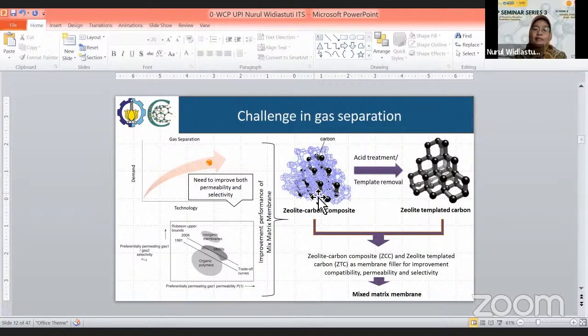The carbon source is impregnated inside the pores of the zeolite, followed by pyrolysis at high temperatures, normally above 800 degrees Celsius, and then we get the zeolite carbon composite. After that, we break down the structure of the zeolite using acid treatment to produce the zeolite templated carbon, which is called the negative structure of the zeolite. So in our research, the zeolite templated carbon and also the zeolite carbon composite were used as fillers for improving the compatibility, permeability, and selectivity of mixed matrix membranes.